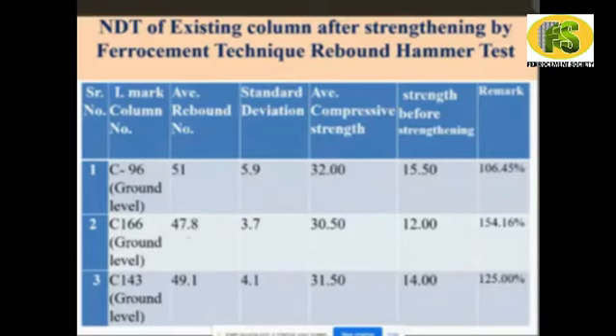Second, this is the second column, C166. Average rebound number is 47.8. Standard deviation is 3.7. Average compressive strength is 30.50. And before strengthening, the compressive strength using rebound hammer is only 12. That means it is increased by 154.16%. Similarly, for column C143, rebound number 49.1, standard deviation is 4.1, average compressive strength 31.50, and the compressive strength before strengthening is 14. Here it is observed that the improvement in the strength is 125%.